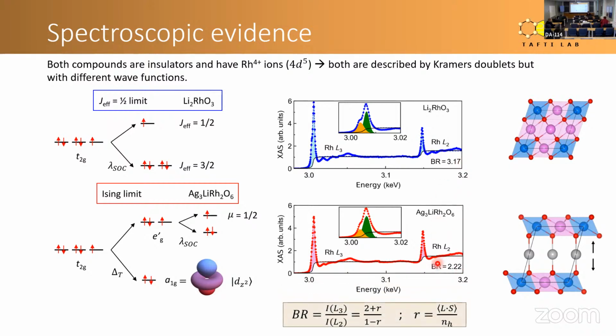There is some proper theoretical treatment of this branching ratio, which I'm not going to go through, but to summarize, the branching ratio will be related to this parameter R, which itself is basically a ratio of the expectation value of L dot S, which is the spin orbit coupling operator, divided by the number of holes. In these two materials, you basically have 5 electrons and 5 holes, so they're the same in number of holes. If you get the branching ratio, you basically get the expectation value of spin orbit coupling.